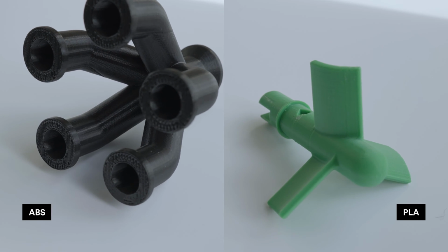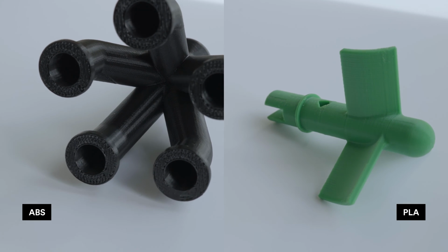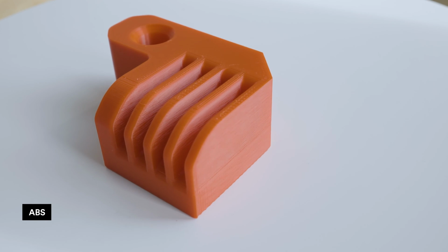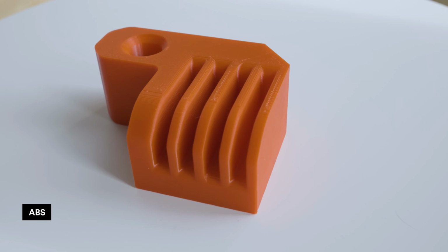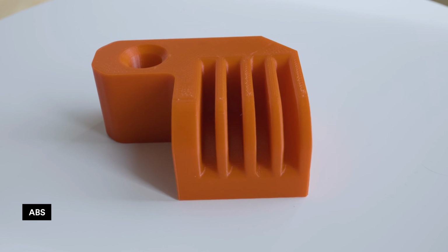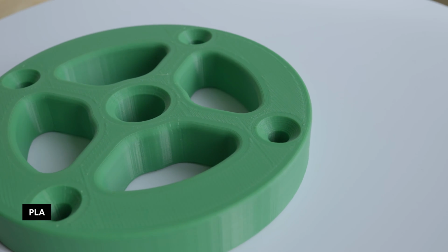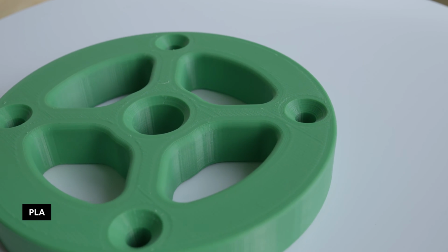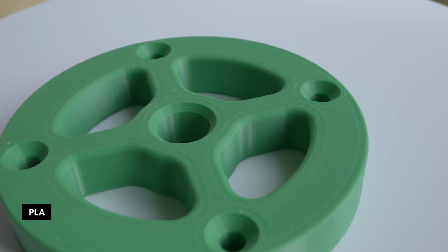ABS and PLA can both be used to create dimensionally accurate parts. They can print details down to 0.8 millimeters and minimum features down to 1.2 millimeters. For connecting or interlocking parts, a tolerance of plus or minus 0.5 millimeters is recommended, and using a minimum wall thickness of 1 to 2 millimeters will ensure adequate strength in wall elements.